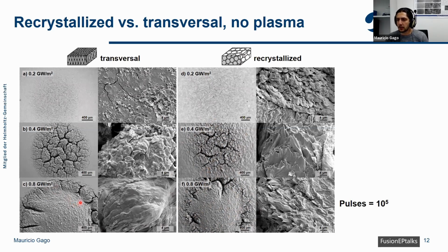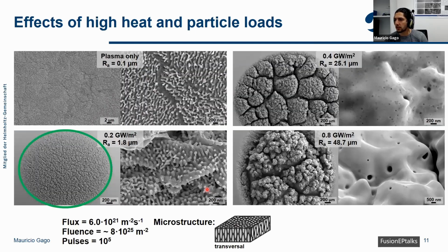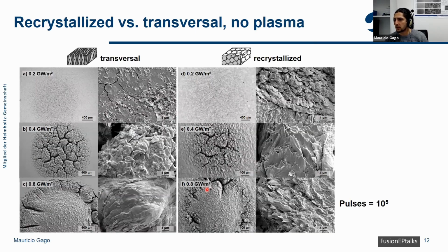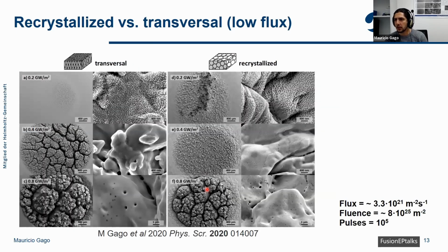It is expected that the cracks start on the edge of the laser spot, because here the temperature gradient is larger. But why they didn't form in the center, this is maybe harder to explain. But also we see that there's more cracking than before. For example, in some cases, which is an indication of hydrogen embrittlement, which we will see now that we have recrystallized versus transversal as well, but with a low flux of hydrogen helium plasma applied.